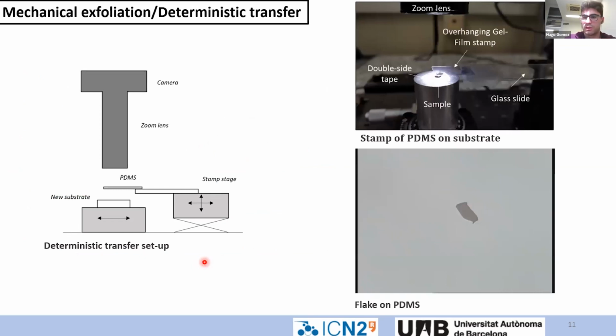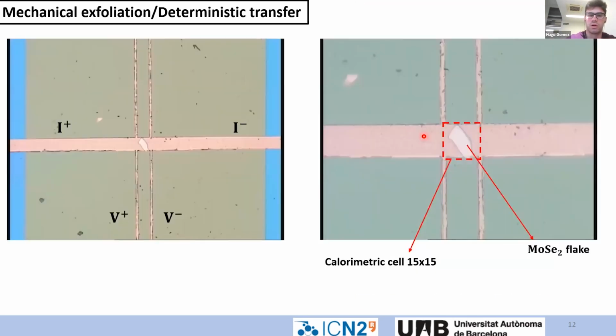Once we have done the calibration of the calorimetric cell, we have to transfer our 2D material, which in our case is molybdenum diselenide, onto our calorimetric cell. We do it by mechanical exfoliation, and I'm sure most of you are familiar with this technique. We exfoliate the material and put it on a viscoelastic polymer. We press it against our calorimetric cell, and by slowly peeling off, the flake remains over the cell. This is an optical image of our calorimetric cell, and we can see the flake completely centered around it.